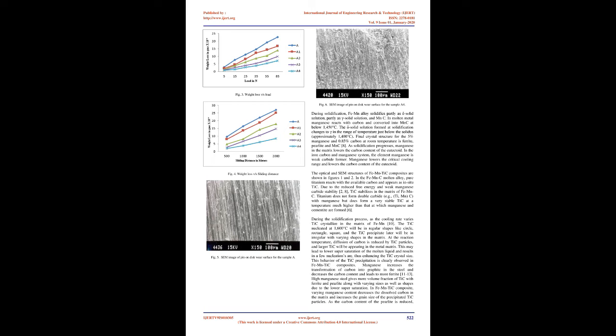Due to the reduced free energy and weak manganese carbide stability 2,8, TiC stabilizes in the matrix of Fe-Mn-C. Titanium does not form a double carbide, e.g., Ti-Mn-C, with manganese, but does form a very stable TiC at a temperature much higher than that at which manganese and cementite are formed. 6. During the solidification process, as the cooling rate varies, TiC crystallizes in the matrix of Fe-Mn-C.